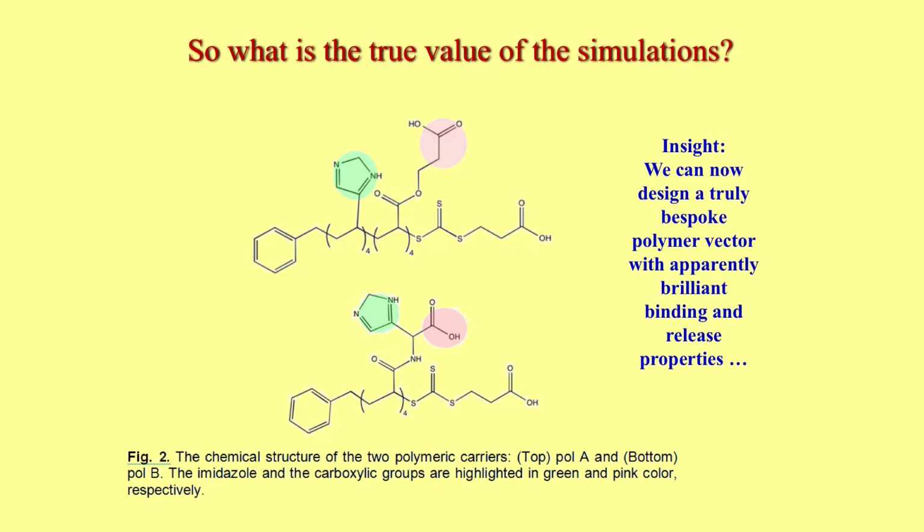2 different designs you see here. One is a block copolymer where one side has weak acid groups, the other side has weak base groups. And the lower figure is an alternative where you design into a monomer both weak acid and weak base groups, and then just make a short strand polymer from that particular monomer. 2 different ways to do it. The idea here now is that you go from negative charge at ambient pH 7, when you drop down to pH 4.5, the whole thing goes positive. And so it should just blow apart from the positively charged protein drug and get really more efficient release.